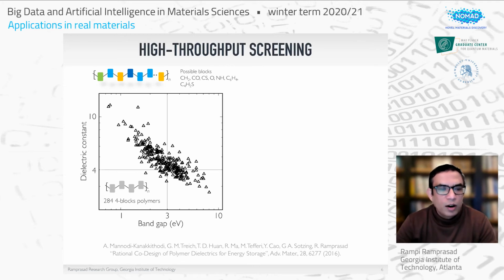Now, when you consider these 7 blocks and make your hypothetical list of polymers, it turns out that you will have a few hundred cases that are kind of unique. And for those almost 300 cases, we did DFT calculations to predict the dielectric constant and the band gap, right? There are probably DFT people in the audience. For those aficionados of DFT, I want to mention that the band gap was computed using hybrid exchange correlation functionals, and the dielectric constant was computed using density functional perturbation theory.